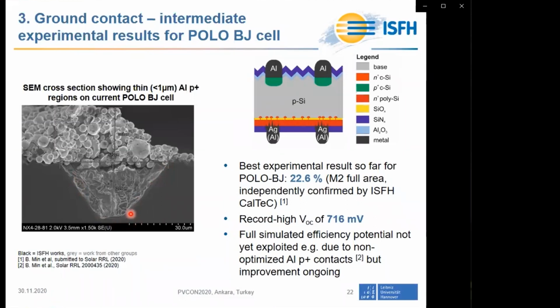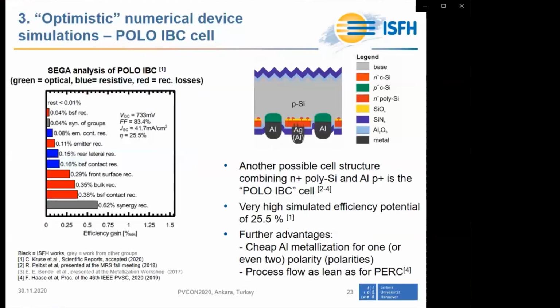They are quite narrow, surprisingly narrow, and not as good as we measured on test structures. One reason might be that for the full cell we also have to find a compromise for the firing temperature for the front side and for the rear side, and therefore the BSF formation is not yet as perfect as measured on our test structures. Nevertheless, we are making good progress here, and we are confident to improve our results quite soon.